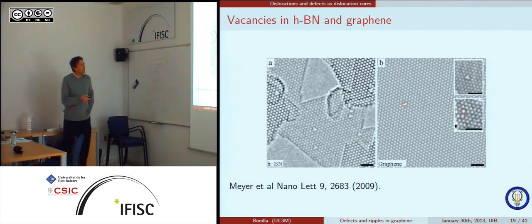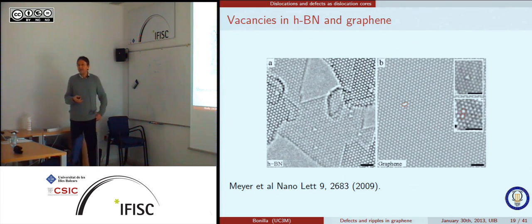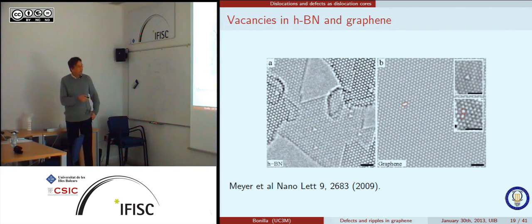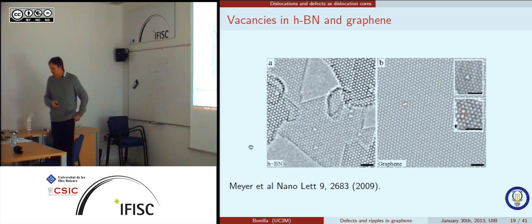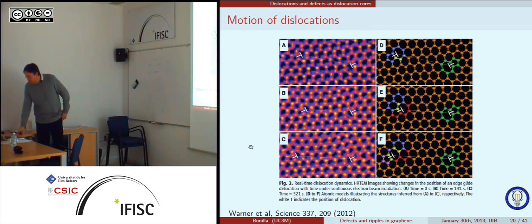These are experiments that were done with vacancies. This is hexagonal boron nitride. So here it's still a honeycomb lattice. But one sublattice has the boron atoms, the other one the nitrogen atoms. So it's not exactly as the graphene one. This one produces these symmetric processes. This is graphene, so you see these asymmetric ones. Of course, these are snapshots.